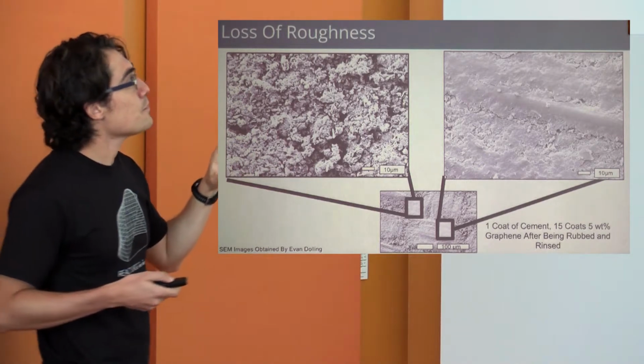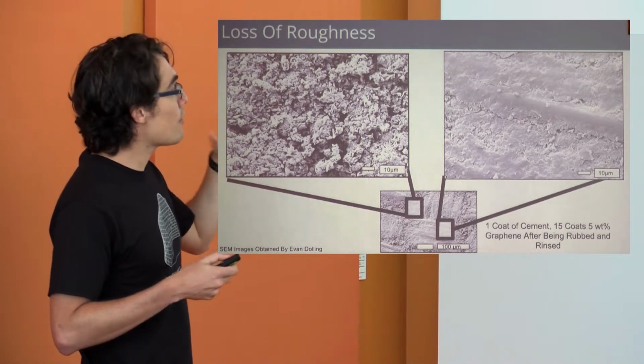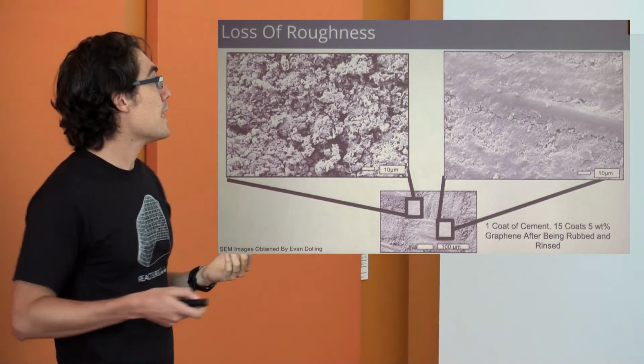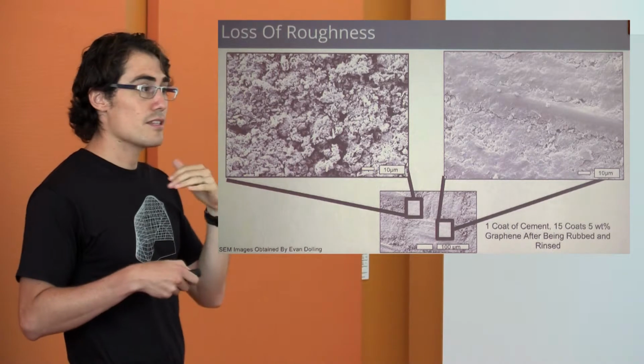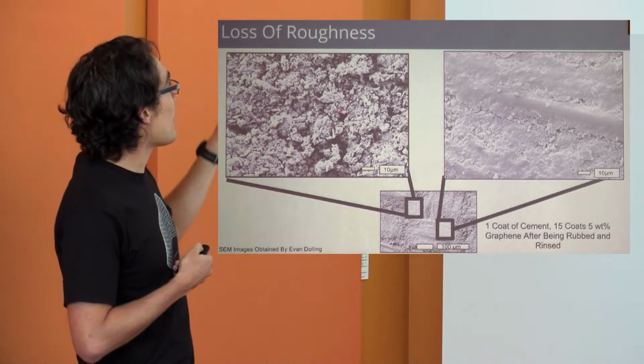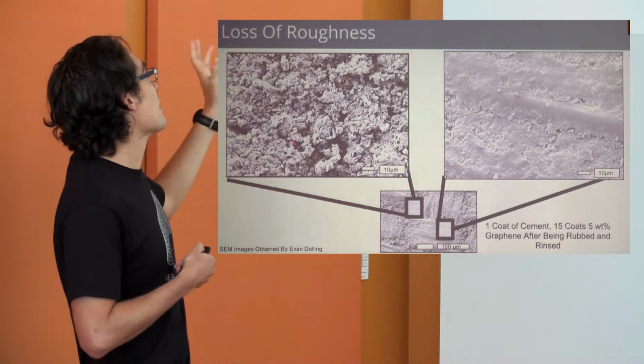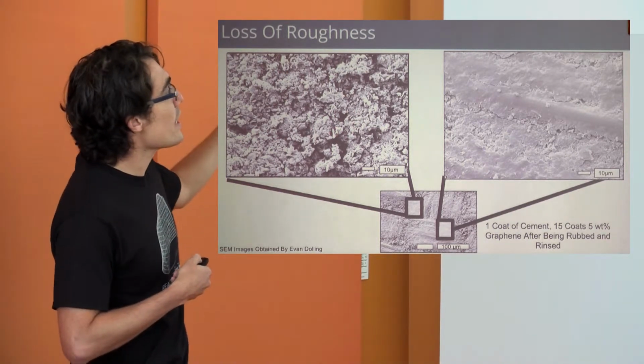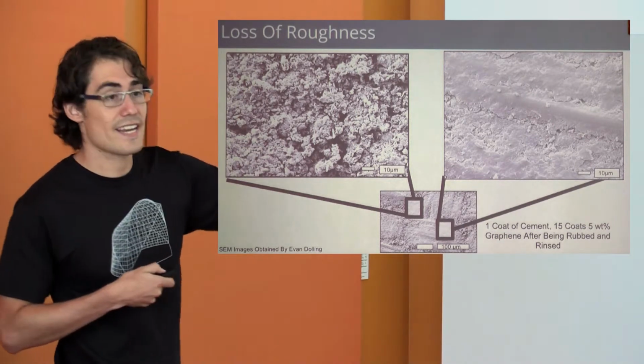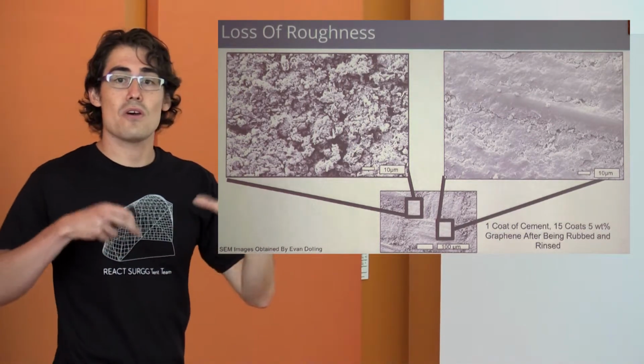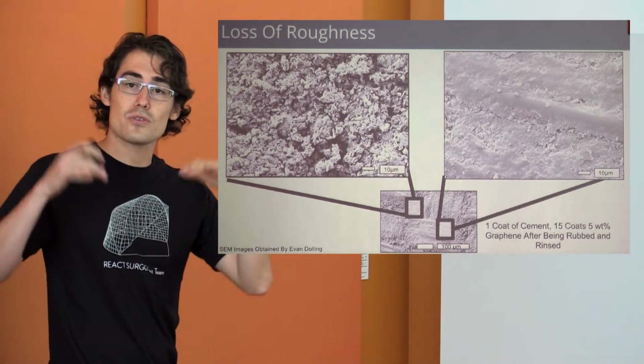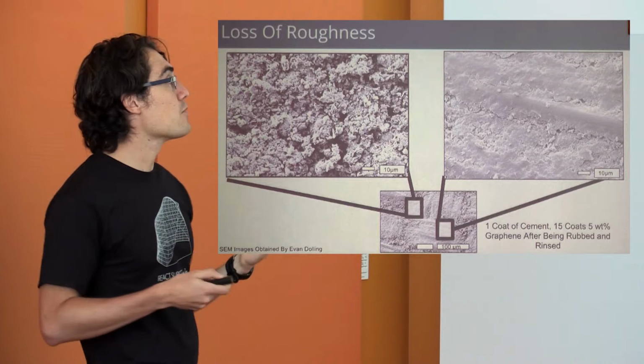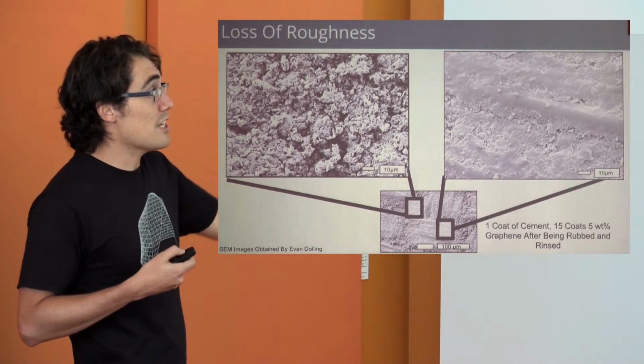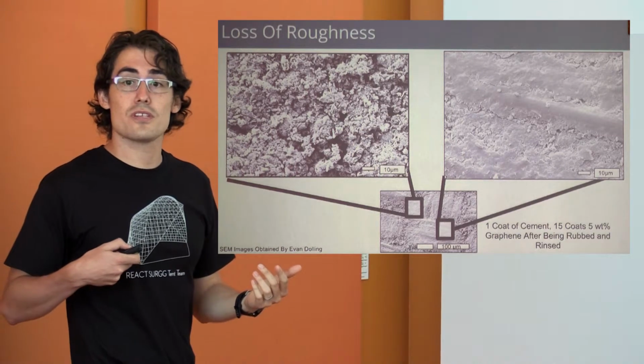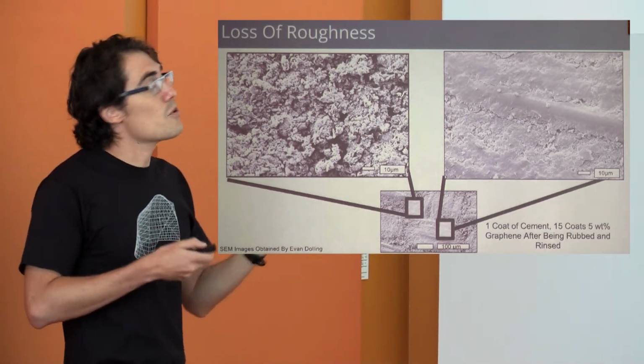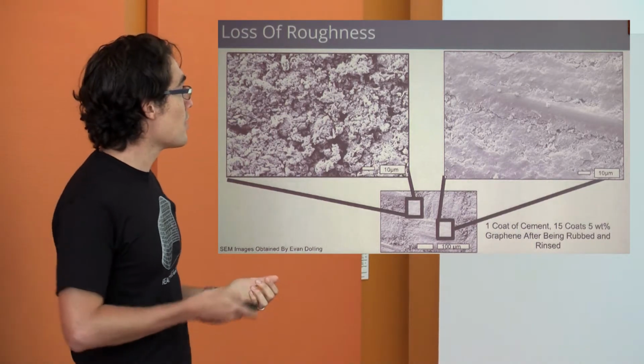Here we can see why the graphene by itself lost its properties, both the slippery nature and the super hydrophobic nature. Here we can see the roughness. There are bigger features, smaller features, and once it was rubbed, it gets pretty much flattened out. And this messes up the whole theory that we talked about, creating those nano and micro surfaces to allow us this super hydrophobic state. Also, it's possible that some of the fabric might have gotten exposed, and this will make it more similar to the fabric than the actual coated samples.